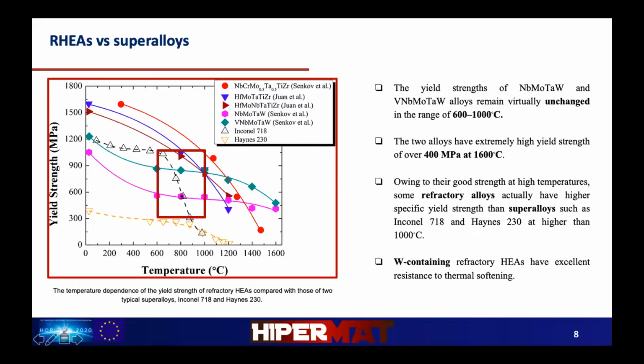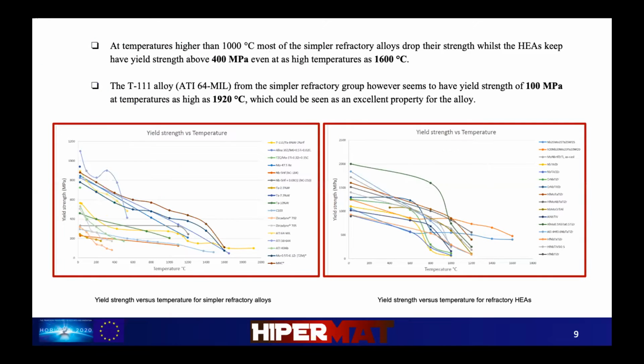refractory high entropy alloys have virtually remained the same, unchanged over the range of 600 to 1000 degrees Celsius, whereas the superalloys drop their strength over this temperature range. Also, it is interesting to note that the two alloys have extremely high yield strength, over 400 MPa at 1600 degrees Celsius. Also, the tungsten containing refractory high entropy alloys have excellent resistance to thermal softening.